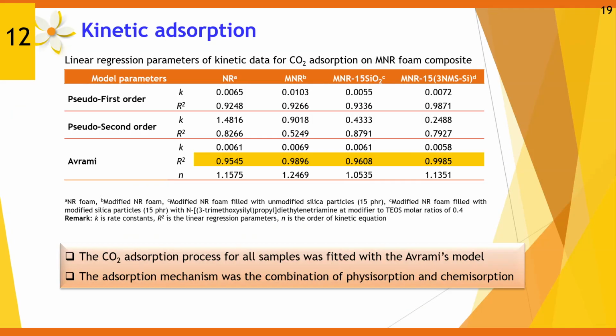Also, the kinetic data for the carbon dioxide adsorption on the modified natural rubber foam composite will be shown in this slide. Three kinds of models are studied, including pseudo first order, pseudo second order, and the Avrami model. The results show that the carbon dioxide adsorption process for our sample fits well with the Avrami model according to the R-square being close to 1. This result can be explained that the adsorption mechanism for the modified natural rubber composite material is a combination of physisorption and chemisorption.